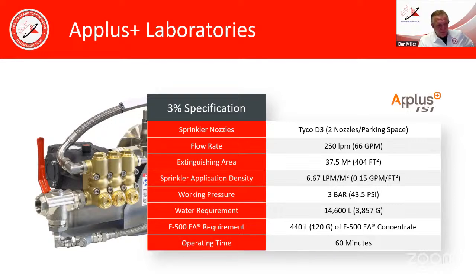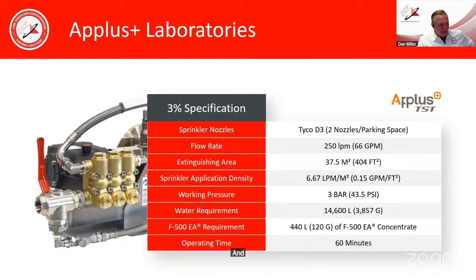Working pressure was 43.5 PSI or 3 bar. The total water requirement was only 3,857 gallons, and that was for the entire 60-minute test of flow. And then the F500 EA requirement for that same time period was only 120 gallons total. Oh, excuse me, not 20 minutes, 60 minutes. So if we reverse the math out of that, 60 minutes, 3% at 0.15 GPM per square foot, you come up with the total used was 120 gallons.